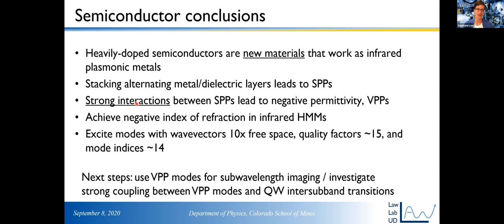The short answer to your question is, in order to get plasma wavelengths in the infrared, you need doping densities of order like 10 to the 19 electrons per cubic centimeter or 10 to the 20 electrons per cubic centimeter, which is an enormous amount. And it turns out the gate voltage you need to control that is so big that it causes dielectric breakdown. And if you use modulation doping, you actually don't get enough doping to make it work in the infrared. It's a great idea, and I would love to have a way to make it work, but unfortunately, we cannot make that work.